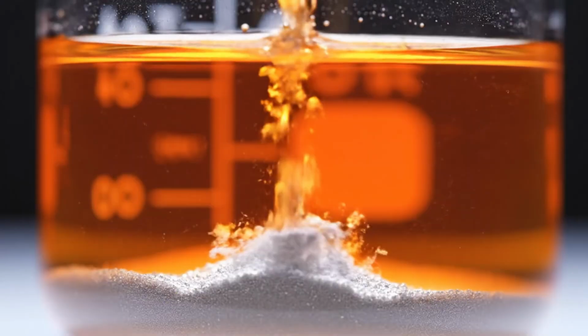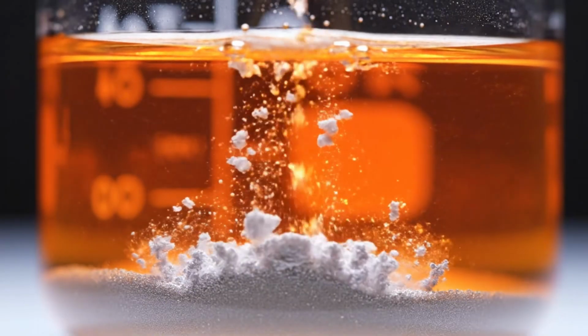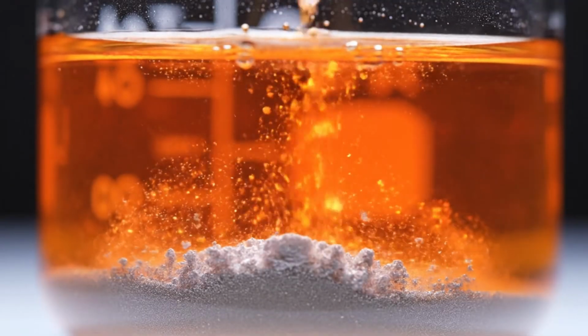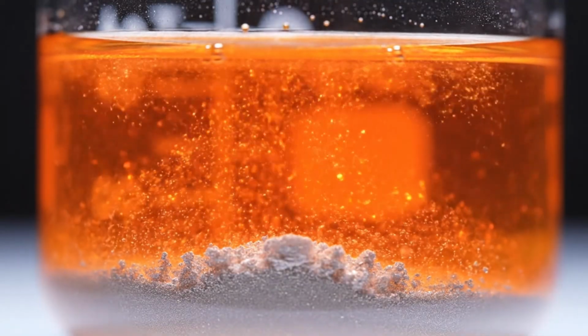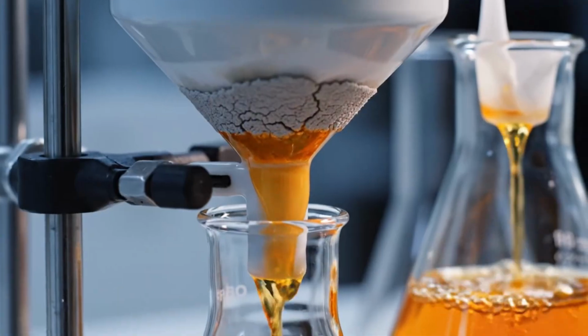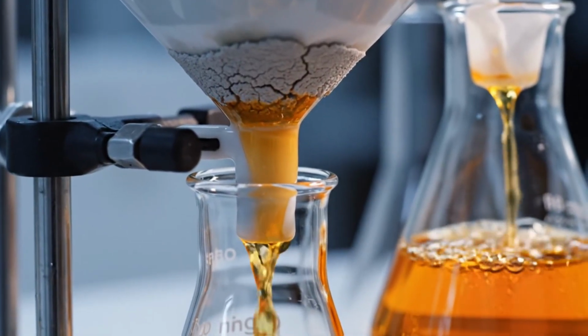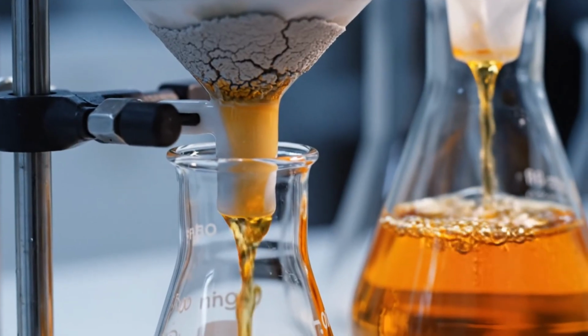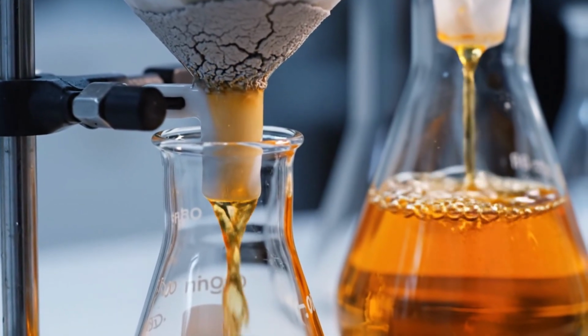The acid consumes the metal, leaving silver behind as a white chloride sludge, while the gold atoms float freely in the toxic and corrosive bath. We filter the solution through vacuum pumps, catching the debris and ensuring only the liquid gold chloride passes through to the next glass reaction vessel.